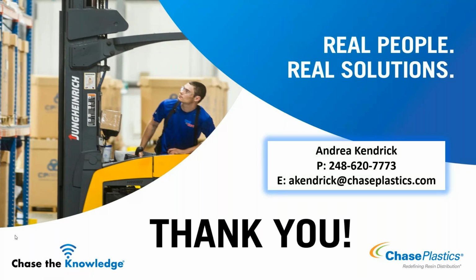But yes, that's a very big concern. In my past life, I used to mold some long glass fiber. We ran into some problems with that where we did some burn-off testing and had a lot of glass powder, not so much retention of long glass fiber. High back pressure and things like that on the injection molding machine can also chop that fiber up as you're plasticating and building your shot.